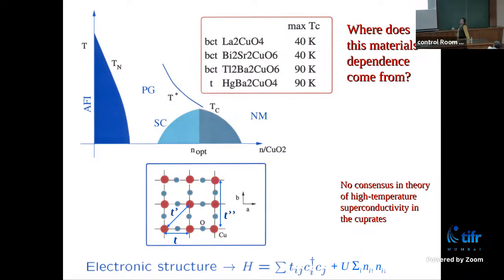Now, it's still debated what causes this superconductivity. Of course, one idea is the strong correlation that makes it superconducting, but that may not be the complete story. So we'll not get into that debate. What I just want to point out is how much variation of TC you have even within the same cuprate family. Lanthanum cuprate, where it was discovered by Bednorz and Müller, two solid-state chemists, I love them. Maximum TC is 40 Kelvin. The same cuprate, you put some mercury, barium, etc., TC becomes 90 Kelvin.